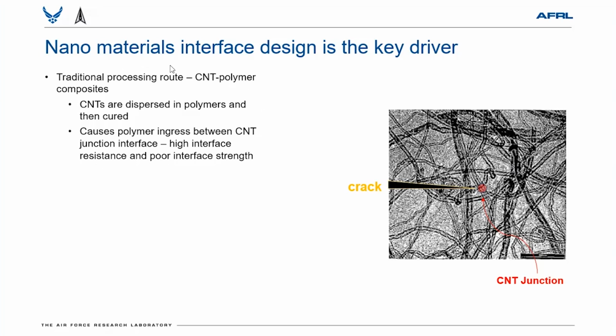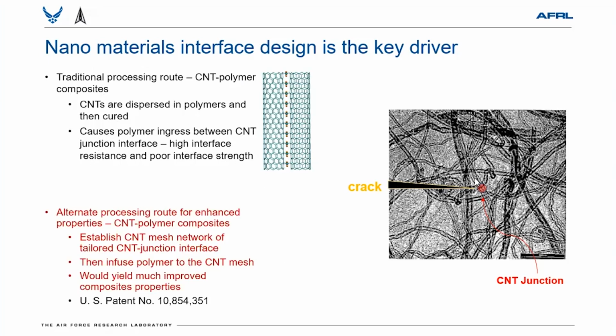So in traditional processing route, you disperse carbon nanotube in polymer and hope they will provide the improvement, but that doesn't happen because as soon as you put nanotube in polymer, polymer gets in between carbon nanotube, hence interface will not be as robust. Whereas before you put the nanotube network in polymer, you create the network junction by either heat treating to weld the junctions or decorate the nanotube with some other metal and other materials. Then by heat treating, that creates a network of welded junctions interconnecting nanotube. After you create the network, then you infuse polymer into the nanotube network, and then you have the integrity of network nanotube, and you will get the higher performance.